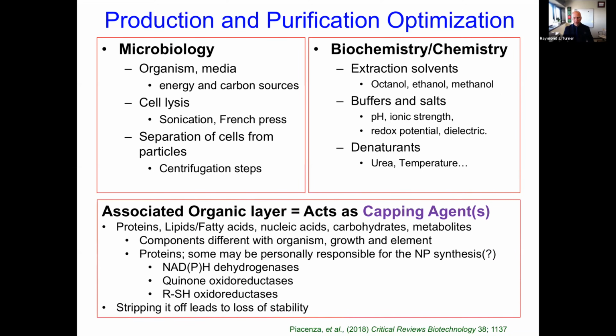One thing about nanoparticles for stability to control size: if I'm synthesizing it with chemistry or using a laser, I'd want to cap that material with some sort of compound that would stabilize it so it wouldn't aggregate any further. Well, the bacteria are producing the capping materials from their own biochemistry. So they're going to be capping proteins, lipids, fatty acids, nucleic acids, carbohydrates, metabolites, everything that would be in the metabolism of what's going on. To date, we've identified a few specific proteins that make sense as the actual enzymes catalyzing the reduction process towards the material, and then those proteins become the capping layer for the stability.